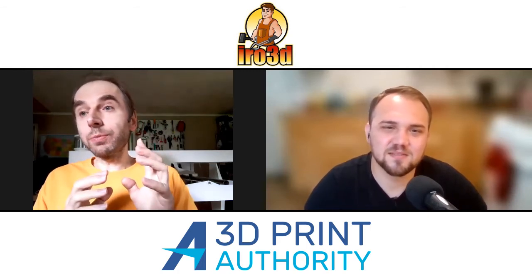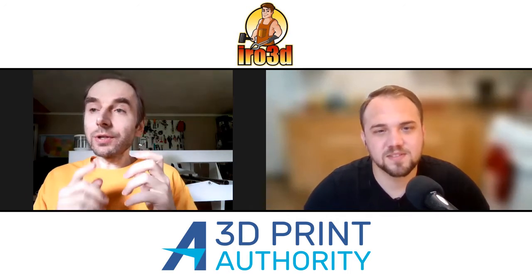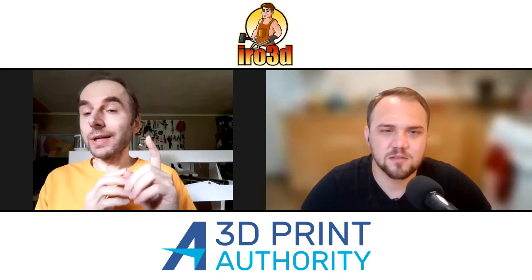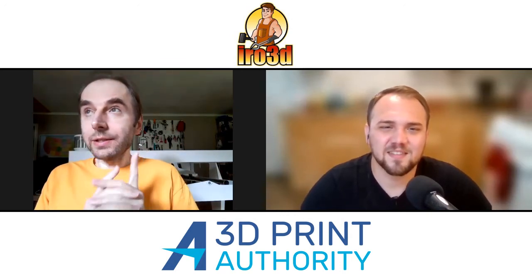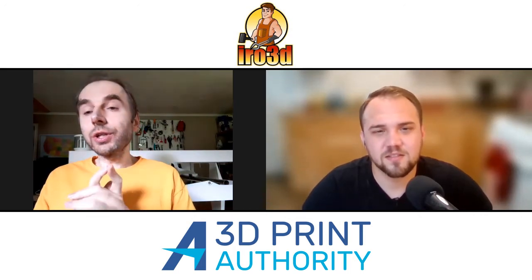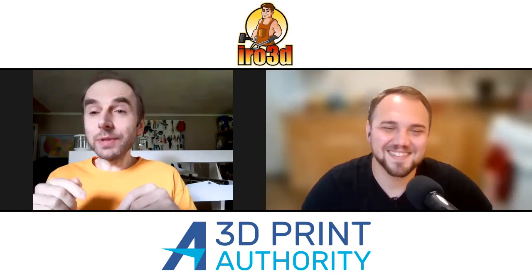You preserve the shape. You don't need to correct it in the software to account for shrinkage, because the shrinkage is also non-uniform. So whenever you have shrinkage, you have distortion. This method does not have this problem. I think this is one of the main advantages. But you can still use sintering, and you'll have shrinkage with the SPD process.